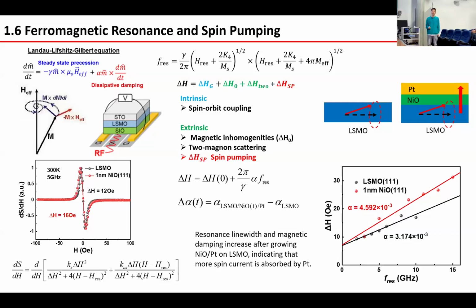So once the magnetic material absorbs at the resonant field, we can obtain the derivative absorption peak in this figure, and this line can be described by the following equations. And there is also a relation between the resonant frequency and the resonant field, expressed by the Kittel equation. And the resonant linewidth contains three components. For example, the intrinsic one comes from the spin-orbit coupling, and the extrinsic component comes from the magnetic inhomogeneity and two-magnon scattering. And there is also spin pumping at the interface.